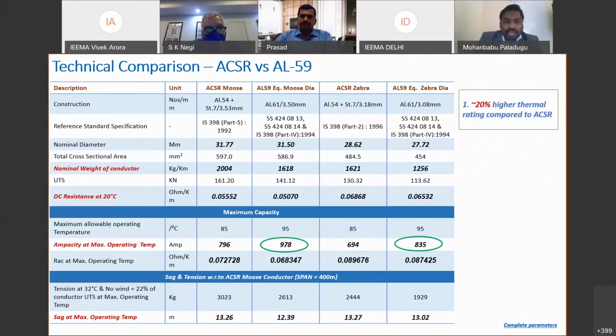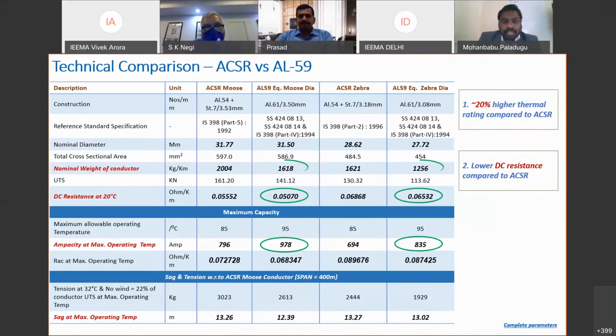So here, the ampacity of the AL59 conductor is generally 20% higher than the ACSR Moose. It's 20 to 25%. And with reduced DC resistance, the DC resistance is lower than ACSR Moose. That means the losses are less at the rated capacities also. These are the two major electrical benefits we are getting from the AL59 Moose. One is the higher rating capacity, higher thermal rating. The other is lower losses.